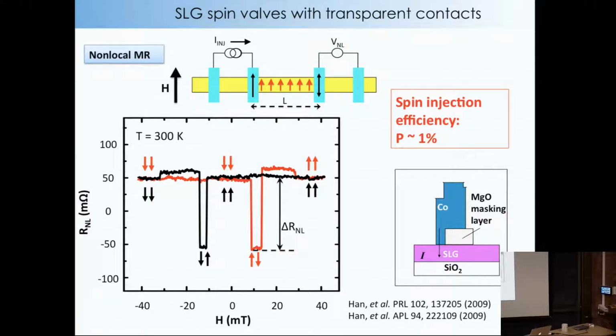And then you'll go from positive to negative. You'll see the same thing, but since the ferromagnets are hysteretic, you'll start positive, parallel, and then anti-parallel, and then parallel. And these extra little jumps are because if you want to do one-step lithography, you can make these outside guys ferromagnetic too. But that's a small effect. It's not a big deal. Okay? And the efficiency of the spin injection, the polarization of the injected carriers is about 1%. So that's not too high.